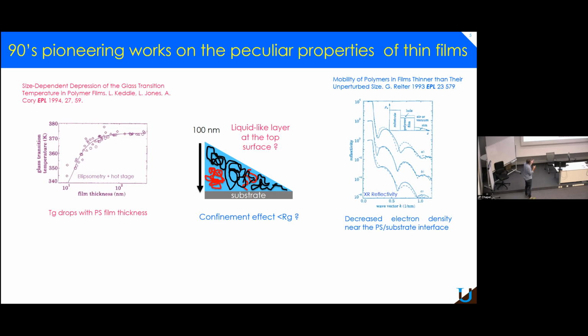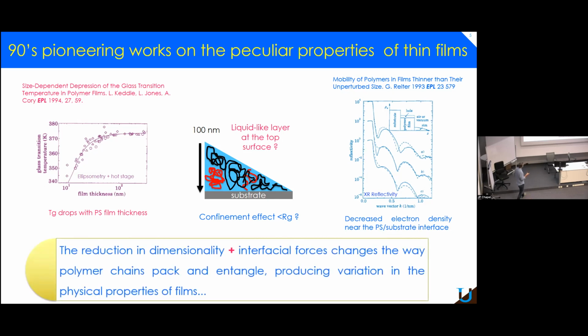So the picture that people started to have at that time is that probably the effect on polymer film is a double effect. There is an interaction with the substrate and the presence of the free layer on top. So at the end, basically, the reduction in size plus interfacial forces changes sometimes the way the polymer chain can pack or even entangle, giving rise sometimes to properties that are quite different from their bulk counterpart.